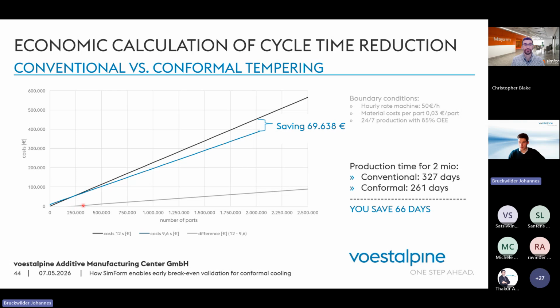You may recognize that this goes below zero. Why? Because we have in the beginning like the 8,800 euro as an investment, as this was a one cavity tool for the conformal cooling. But let's say roughly after 2,500 shots, we have the break-even point, and annually you are saving around 70,000 euro per year. And so that's a huge benefit that you create with the conformal cooling, even if you consider it when you apply a new mold or when you design a new mold.